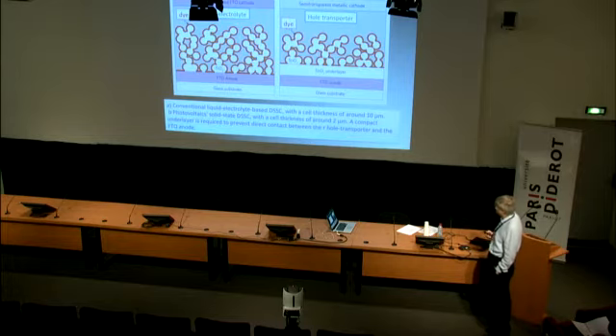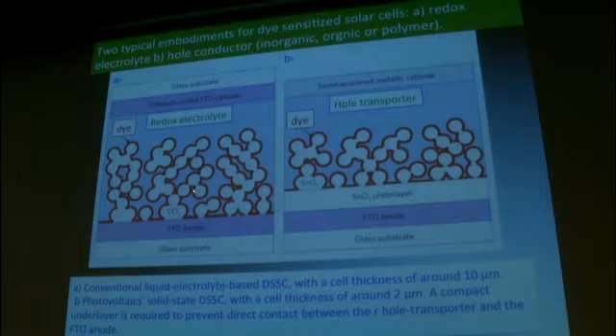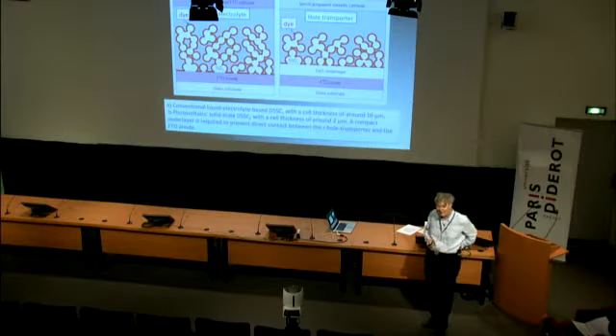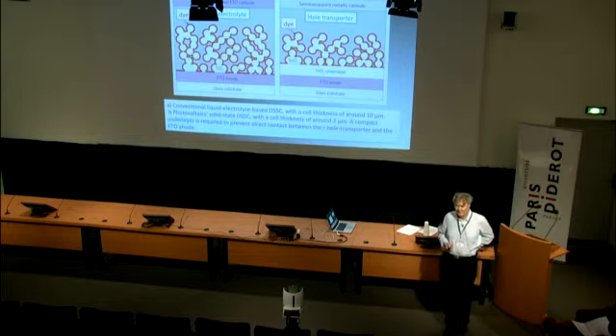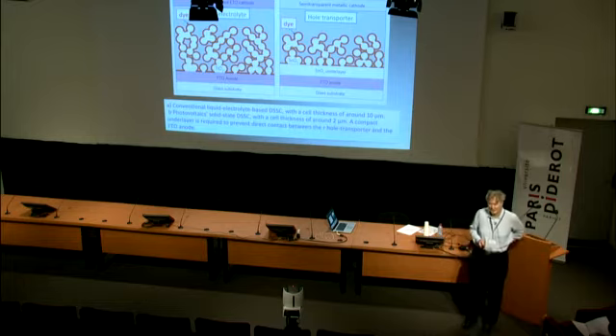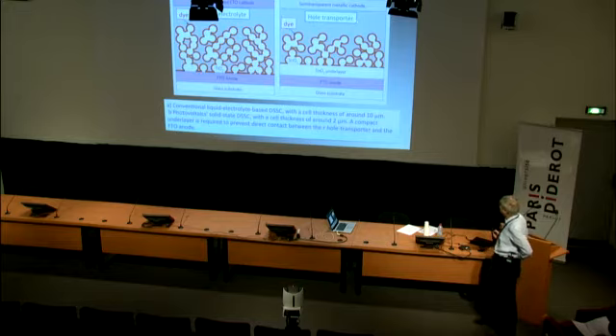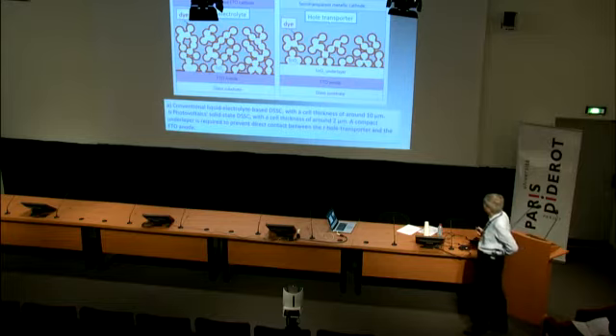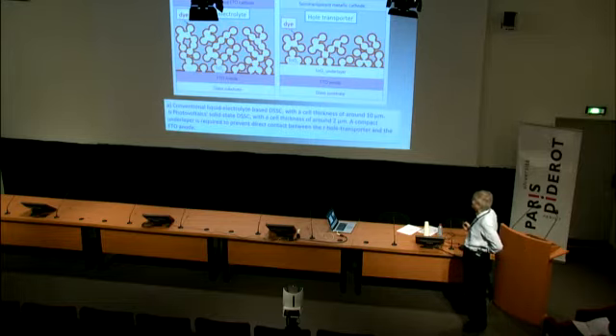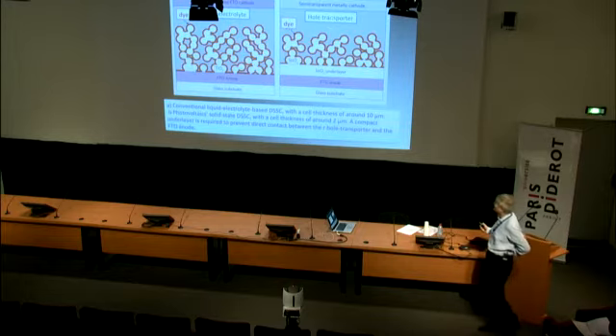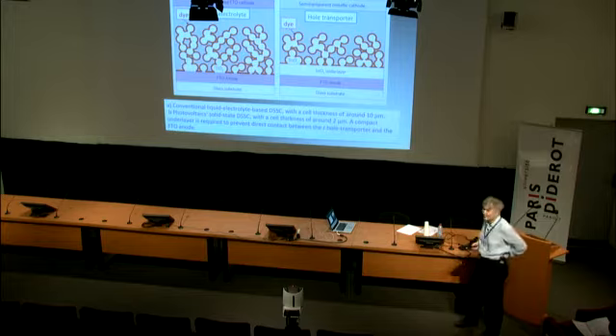But we also have, as I said, this one embodiment which I just described to you, the dye coating these nanoparticles, and then the redox electrolyte, which has been mainly iodide, triiodide, but recently the cobalt complexes have emerged as a very viable and powerful competitor to iodide, triiodide. And so then we have also hole transporting cells. These cells that use polymers or organic or inorganic hole transporters, p-type semiconductors, they still are behind by a factor of 2. I mean, it's 7.2%. That's the conversion efficiency in standard conditions. It's this device, and here we are now between 12 and 13%.